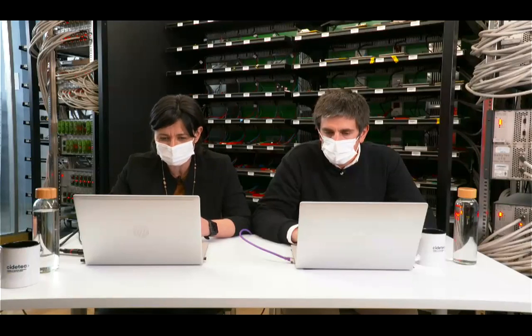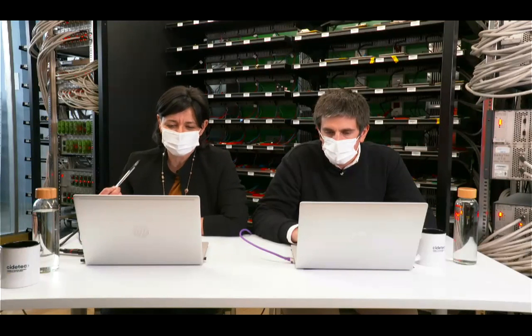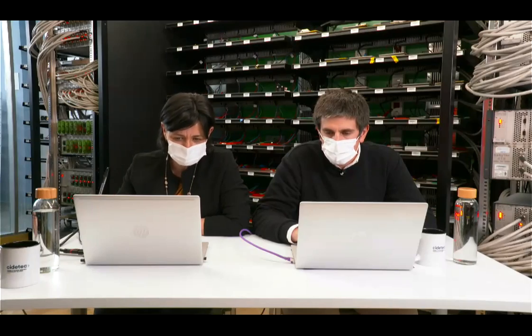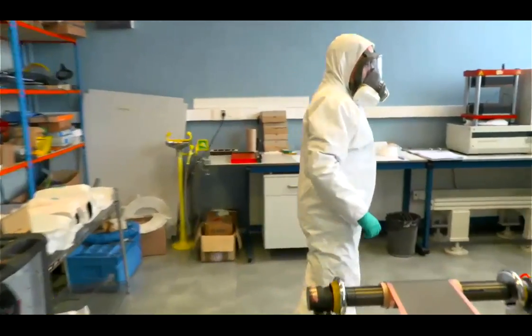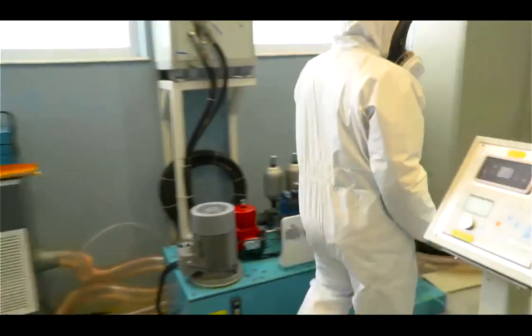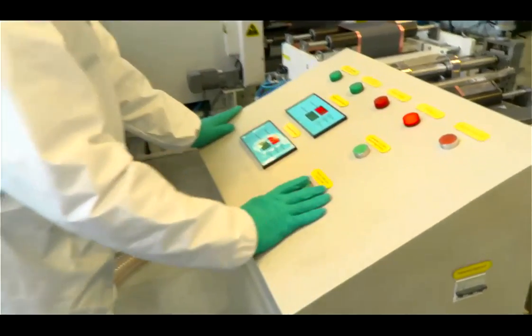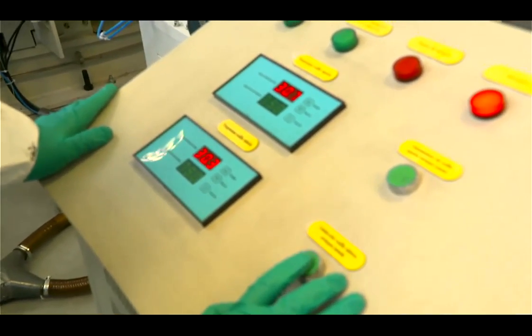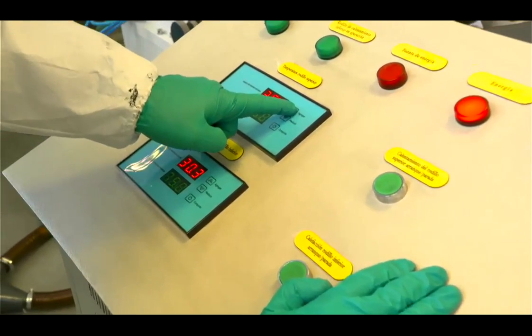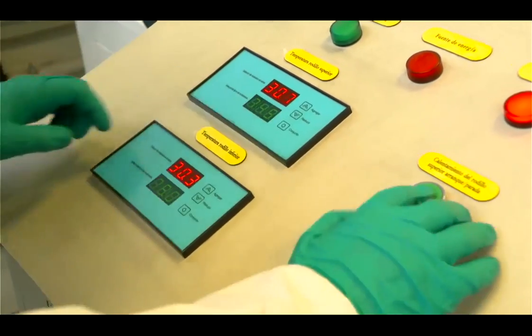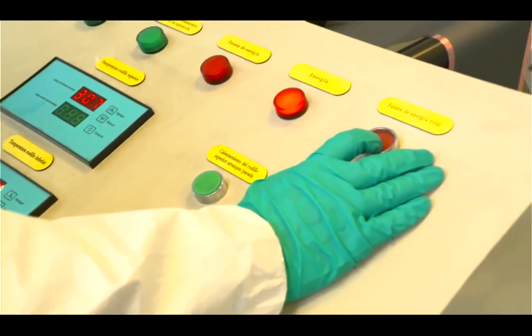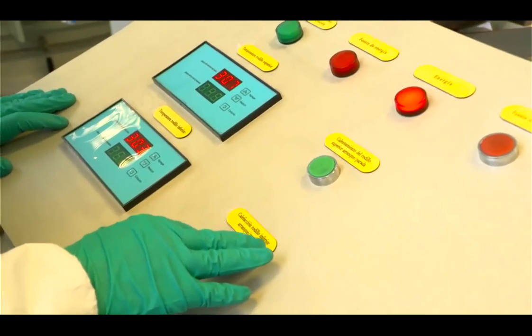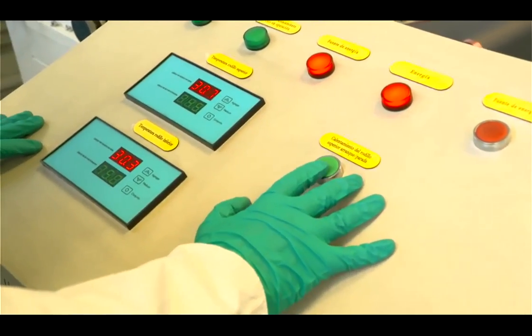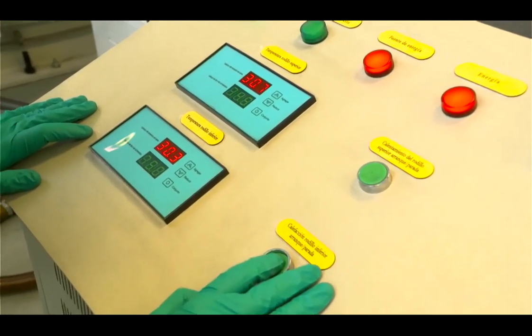Actually, to be honest, we try to avoid heating the rolls, because on one side it's costly to heat the rolls, costly in terms of energy consumption. But the problem is also to cool down the rolls, because it takes a long time to cool down. So we try to avoid that temperature. We use it in very weird cases where the loading is very high and we need to reach very, very thin electrodes, when the densification we are targeting is very, very high. But as I mentioned before, we try to avoid this warming up of the rolls.